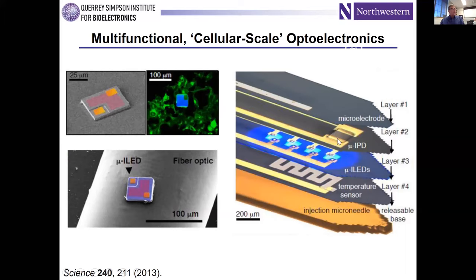You can integrate other devices co-located with these LEDs: a photodetector, maybe an electrode for measuring electrical activity or stimulating neurons electrically, an integrated temperature sensor. I'll come back to that in a second. You stack it all up, and you still have a device that's super thin, maybe 25 microns in thickness. So flexible, in fact, because of that small thickness, it's not stiff enough to even penetrate down into the brain. And so what we do is we define a much thicker polymer microneedle as a temporary support to provide the kind of rigidity that we need to inject these devices down into the brain.